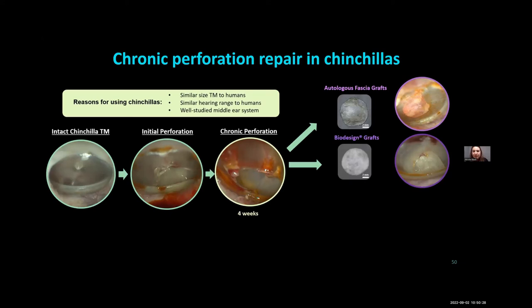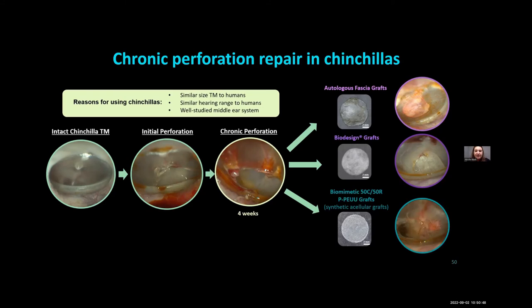Biodesign, which I mentioned, is that predicate device by Cook Medical, that porcine small intestinal submucosa that already exists on the market. And then our biomimetic grafts. In this case, this was the polyurethanes with that fugitive component printed in this 50 circular and 50 radial pattern. So this is a completely synthetic acellular graft that's implanted.